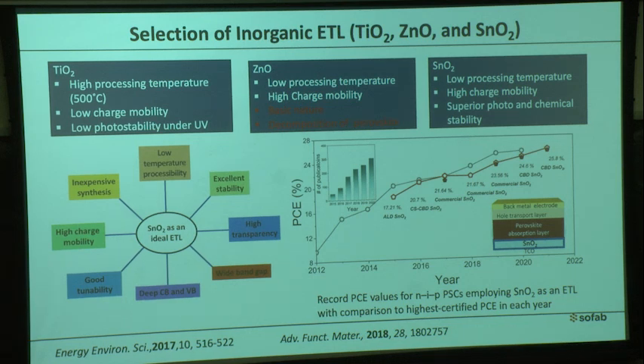After that, people started using tin oxide, and tin oxide largely solved the problems related to titanium dioxide and zinc oxide. We can process it at low temperature, it has high charge mobility, and also higher stability. More people started working on tin oxide, and these are all the useful properties of tin oxide. That's why tin oxide is so popular.